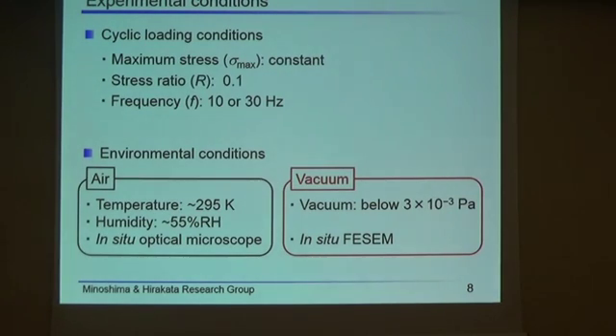And this slide shows experimental conditions. We conducted the experiment under constant maximum stress, at a stress ratio R of 0.1, and at a test frequency of 10 or 30 Hz. And environmental conditions are as follows. The experiments in air were conducted in laboratory air with in situ optical microscope observations. And the experiments in vacuum were conducted below this pressure with in situ FESEM observations.